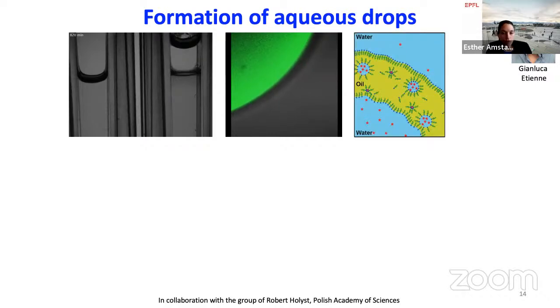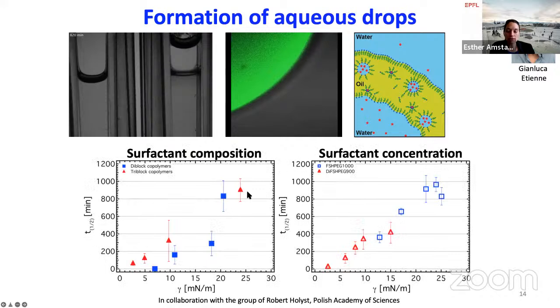And so we synthesized different types of surfactants, all with the same types of blocks, but we varied the length of the hydrophilic block and thereby the interfacial tension. And what we could see is that, yes, the leakiness, which we measured as the time needed to reduce the fluorescence of the core by 50%, linearly scales with the interfacial tension between the water and the oil phase. Here we varied the concentration of the surfactant. Here we varied the type of surfactants that we synthesized.